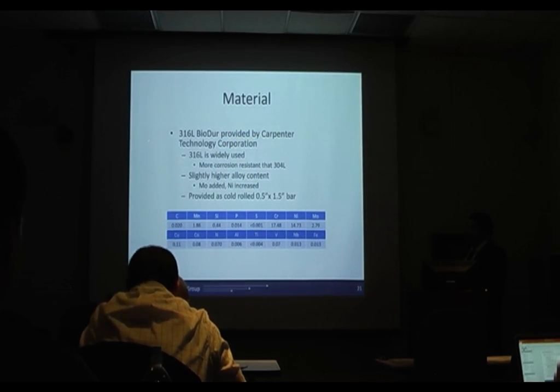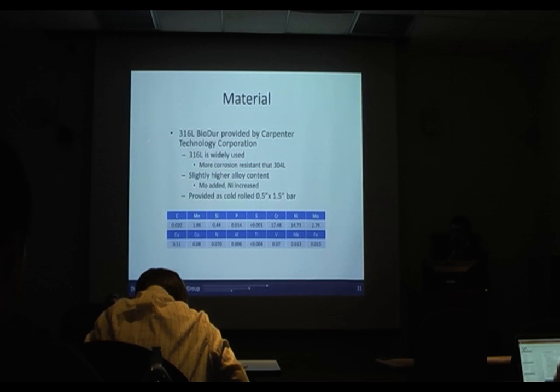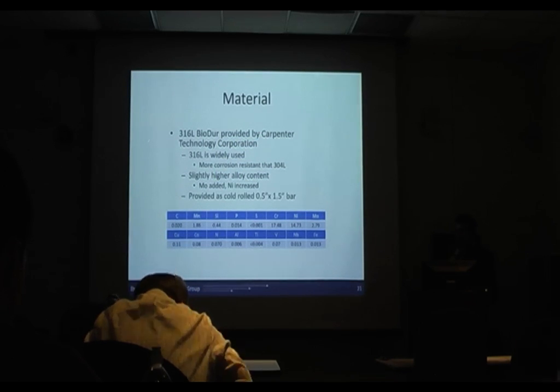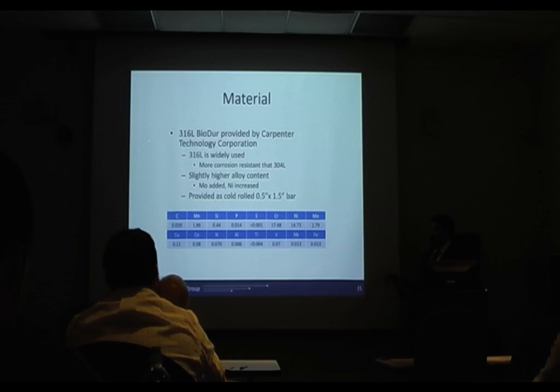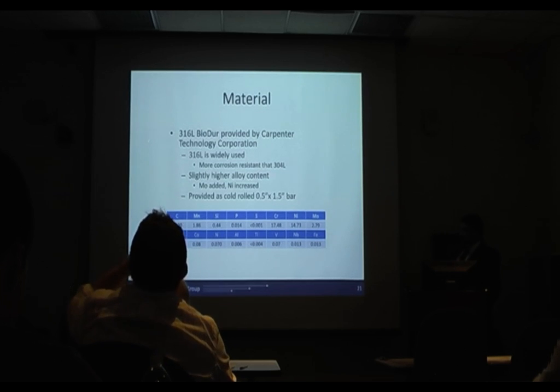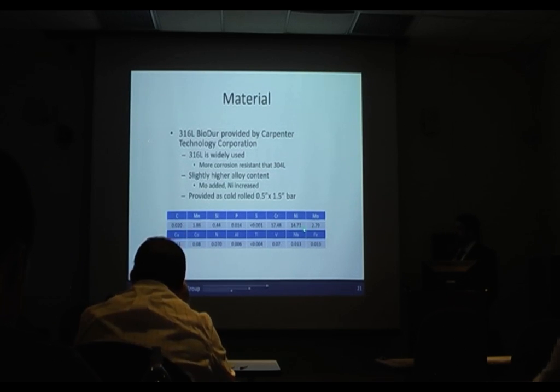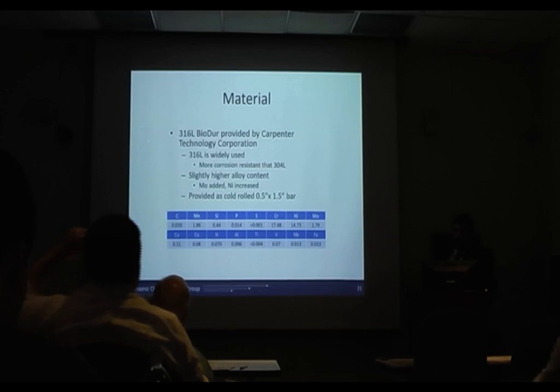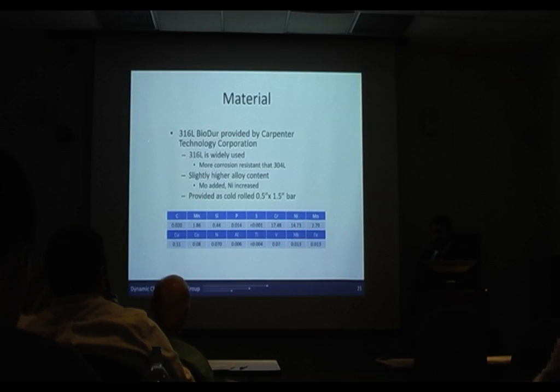The material that we used was primarily 316L BioDur provided by Carpenter Technology Corporation. 316L is widely used, and it's more corrosion resistant than 304. It has a slightly higher alloy content. Compared to the 304, the moly's been added, but in this heat specifically, the nickel's actually even a bit above spec. It's 14.73%, and typically it's not above 14, and in a lot of heats it's down in the 10 to 11 range.